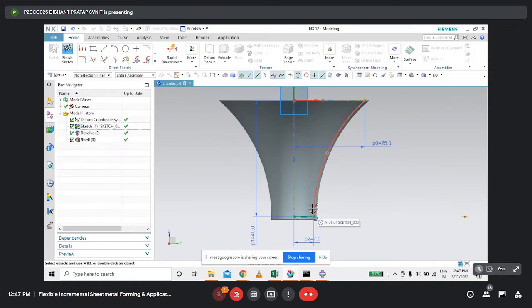So I have created this geometry, and then the depth is decided. The upper radius of the cone is decided by the fixture size. If the fixture size is limited, for instance, our working diameter of the fixture is 50 mm, so we have constrained it to 25 mm. The bottom diameter depends on the tool. Like we are using a 10 mm diameter tool, so we have created 2 mm for clearance so that the tool doesn't interrupt our geometry. Then we created this shell.